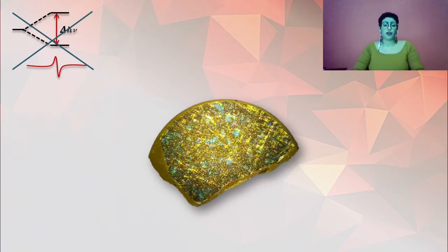Another characteristic of the samples that could contribute to the non-observation of an EPR signal is polycrystallinity. If the samples were formed by microcrystals of the order of hundreds of micrometers, the distribution of the resonant transitions along the magnetic field for each microcrystal oriented in a different way reduces the intensity of the EPR lines, and they may not be distinguishable from the measurement noise.